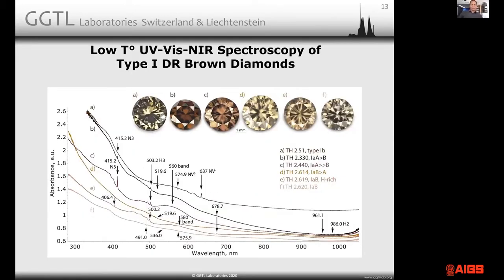Here an overview of the UV visible spectra of brown diamonds. You can see that the brown color originates from a relatively shallow and flat continuum absorption that starts in the near infrared and extends all the way to the UV. The steeper this continuum, the more saturated the color. The more overlaying features you have, the more modifying colors you're gonna observe. So here, for example, in trace C, you see a band at 560 nanometers. That's why the stone is somewhat pinkish, as you can see in the image. And then there is others that barely show anything, like trace F is basically just a continuum with very minor features.